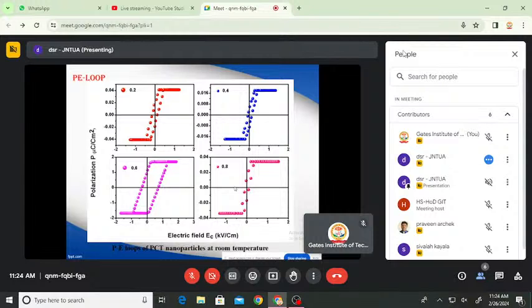So finally, we can conclude that for these lead cobalt titanate nanoparticles with changing cobalt content from 0.2 to 0.8, the mean crystallite size has been reduced to 7 nanometers from 14 nanometers. And the SEM and TEM revealed the formation of flower-like and plate-like nanoparticles. The large difference between particle size and crystallite size may be due to agglomeration. From the FTIR studies, it has been revealed that lead-oxygen, cobalt-oxygen, and titanium-oxygen bonds exist at A and B sites. And from UV visible spectra, the band gap was found to be 3.06 electron volts.